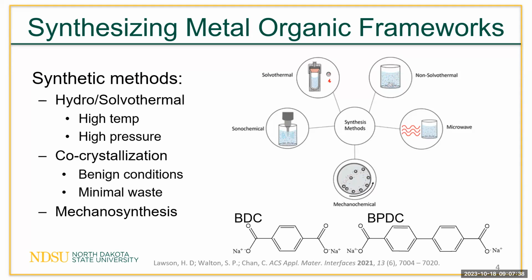Or there's also co-crystallization, which is essentially crashing out or precipitating out the MOF from solution. So this is a very green and benign synthesis. It's just a water solution of metal with a water solution of ligand that we combine together to form these metal organic frameworks and then wash them with water. So it's very green, very minimal waste. The drawbacks, however, are the lower crystallinity compared to solvothermal methods, and that can sometimes actually be used as an asset more than a drawback. So we'll get into that in the applications.